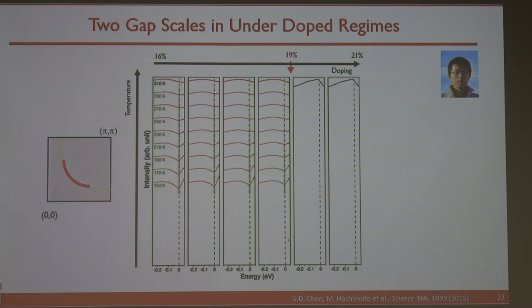Okay. Now look on this side. You notice that nothing happens at the dashed line, until it gets to a point where one peak splits into two peaks. You can see, I can say that red is just one group of spectra, the black is another group of spectra. Just across this boundary from 18.5 to 19.5, it is qualitatively different. Okay, the data.